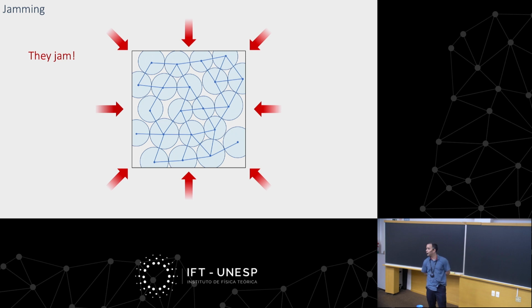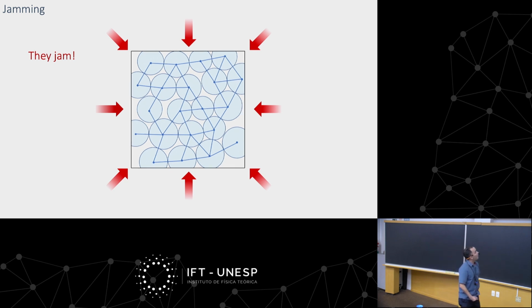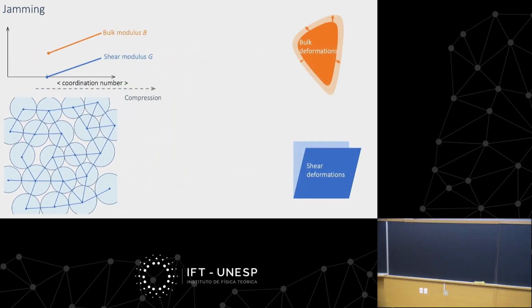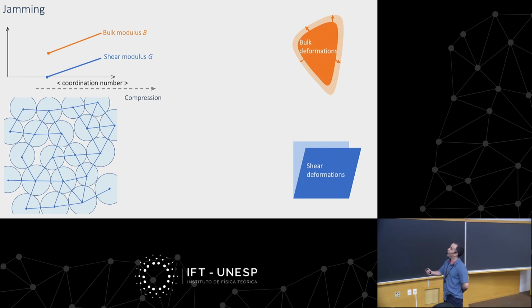Well, at some point, they will jam, and because the set of disks is not uniform, you have different sizes here for these disks, they form this disordered contact network that resists compression. Now, usually you describe this transition in terms of an elastic theory, and you look, for instance, into elastic moduli. When you ramp up the compression, as you reach this critical point, the bulk modulus jumps to a finite value, whereas the shear modulus grows continuously from 0. And this happens right at some critical coordination number for this disordered network.